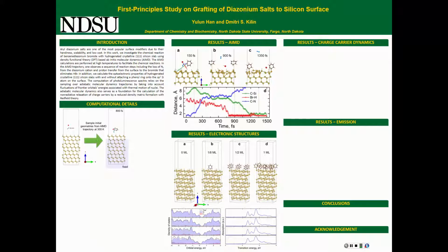And this is a trick that we practice. We increase the temperature to slightly unrealistic values, but then we bring the delay before the reaction launches to limits that we can afford in the simulation. So your question is correct, and it needs to be addressed, at least as an intellectual verbal comment. But very often it cannot be addressed by actual simulations, because it will take too long, longer than we have at our disposal.